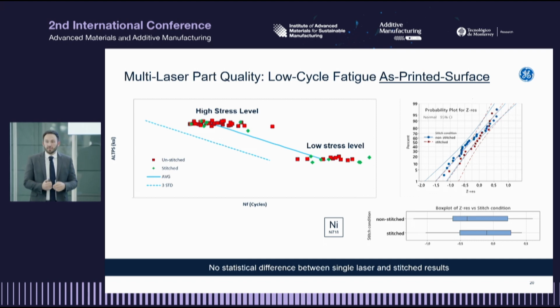Fatigue is also the first one that's going to pick up on any flaw because of the crack propagation that takes place when you have fatigue specimens. So when you look at this plot of two different stress levels, you can see how similar the stitched and the unstitched samples are when you apply the correct type of countermeasures and control the parameter set.